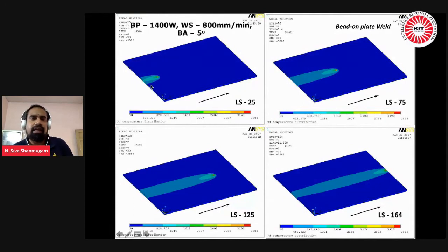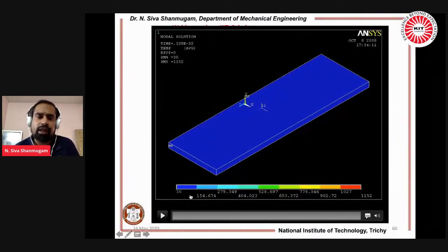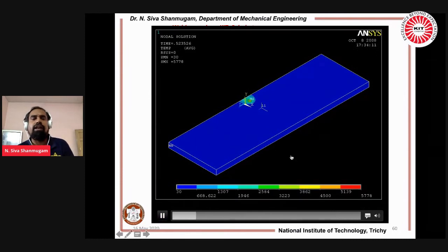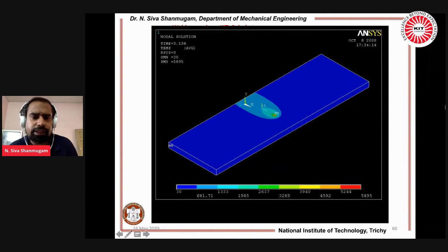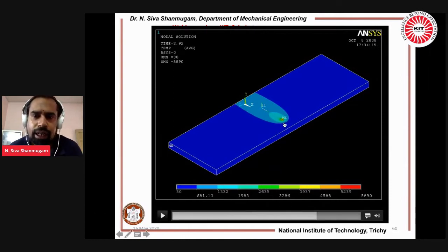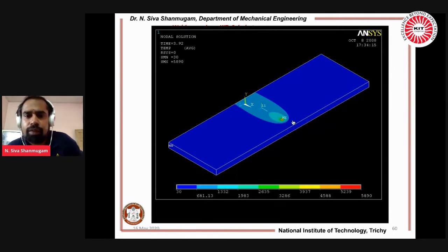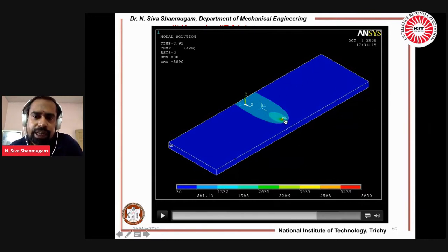At the initial period, when the laser is at the entry, when the laser is at the middle point, and when the laser is at the end. What is the temperature distribution on the surface and along the thickness direction? Both you can do, and this is the video which is giving information about the movement. See, at each step you can see. So when I put the hold, you can see this red color gives a very high temperature, because that is where the heat source is impinging, where the laser is impinging on the material. From that you can easily understand. You see there is only a preheating zone, because it is a concentrated heat source.